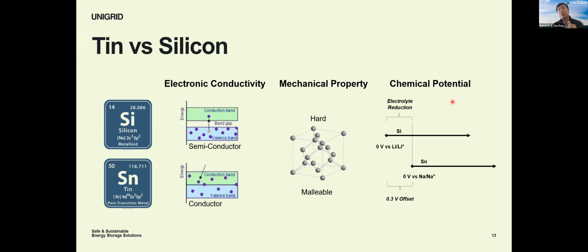And finally, and I think the most important difference is their operating chemical potential. Silicon operates near lithium, which is offset from sodium, where tin is, by 0.3 volts. And near silicon is where all your electrolyte reduction occurs, and then you get all your SEI formation, all your nasty things that happen. Near sodium, there's much less SEI. That's why there's a lot of tin literature out there that shows there's very little side reaction occurring there. Of course, on the downside, you struggle a little bit more on the cathode because everything is pushed towards a high oxidative environment. I think Ruth will know this concept very well as well. Overall, this explains why tin works well in sodium, much better than silicon in lithium.